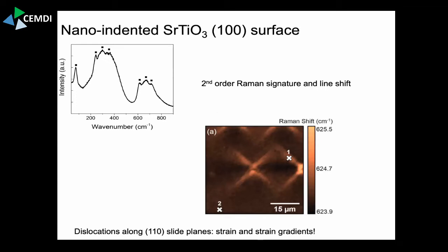So this picture here is basically the shift of this peak here, the left one, as a function of position around. What happens is that during this indentation, we create slip planes. The mechanical stress is accommodated by slipping two crystal planes with respect to each other. There are dislocations building up, and so there's a lot of strain in these areas. But most of all, if there is substantial strain here, and there is no strain here, there has to be a strain gradient. There has to be a transition from a lot of strain to no strain. And that strain gradient has to automatically break the inversion symmetry.